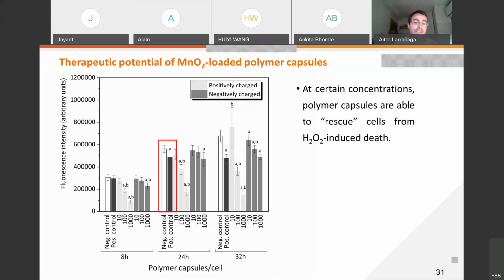So we found a clear difference after 24 hours between the negative and the positive. And this difference was much clearer at 32 hours, which suggests that this hydrogen peroxide in the media is inducing some cell death due to oxidative stress. Interestingly for us, we found that at certain circumstances, such as 10 capsules per cell in the case of positively charged capsules and 10 and 100 capsules per cell in the case of negatively charged capsules, we observe a clear higher metabolic activity of our cells in comparison to our positive control, suggesting that in these conditions, our polymer capsules are able to, let's say, rescue the cells from H2O2-induced death.